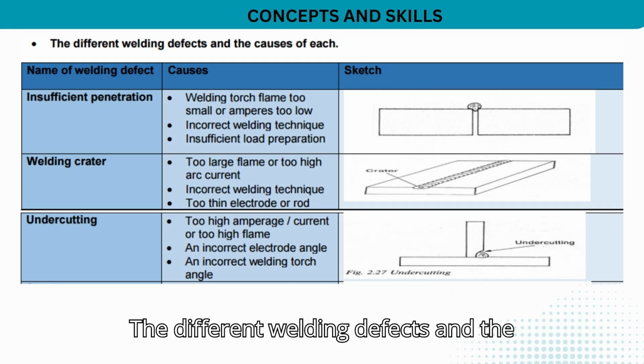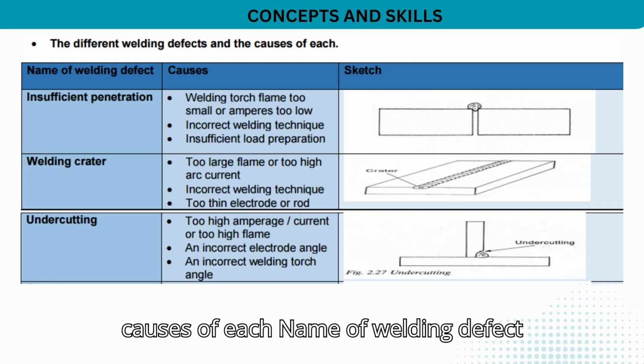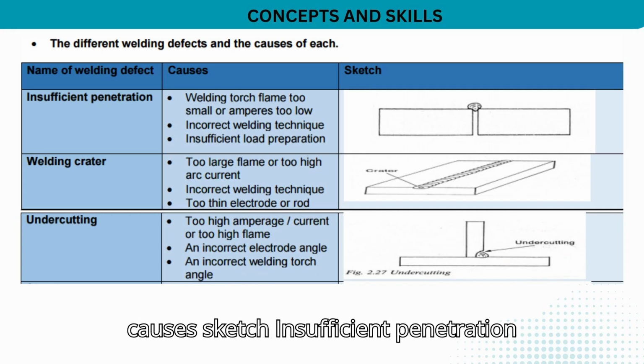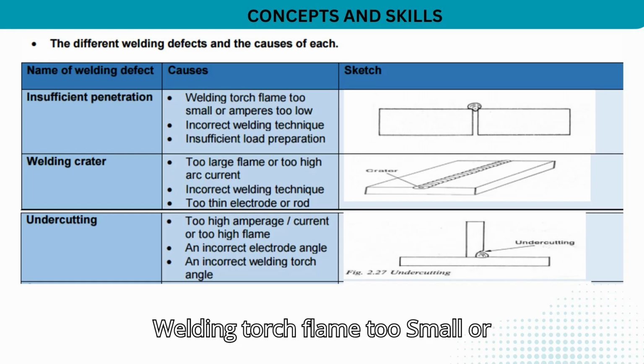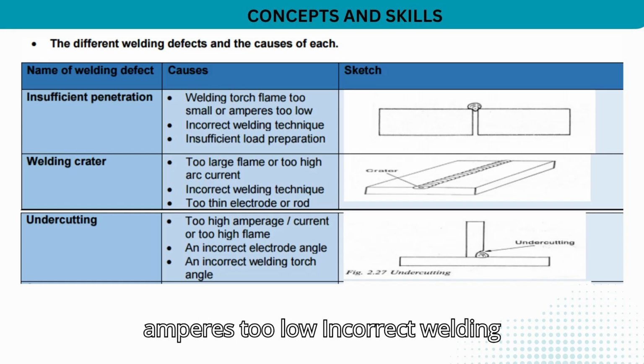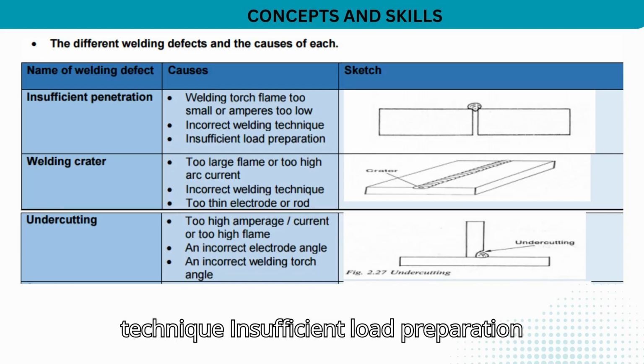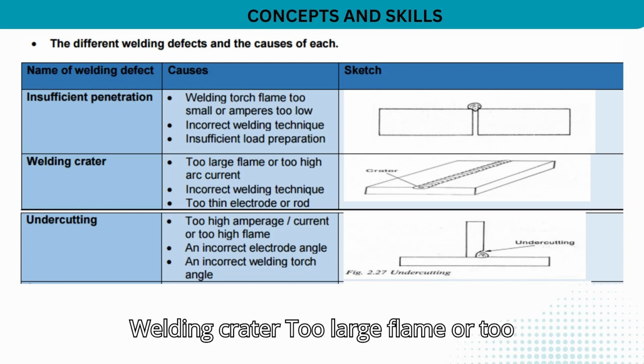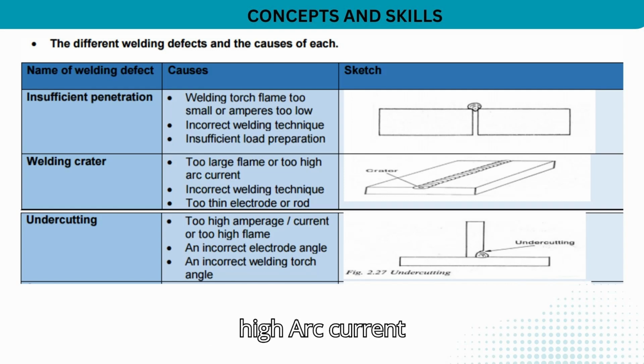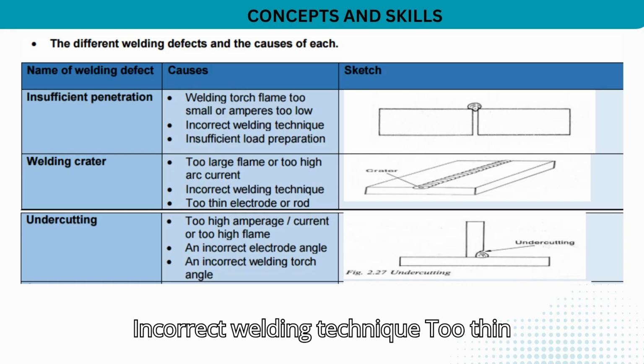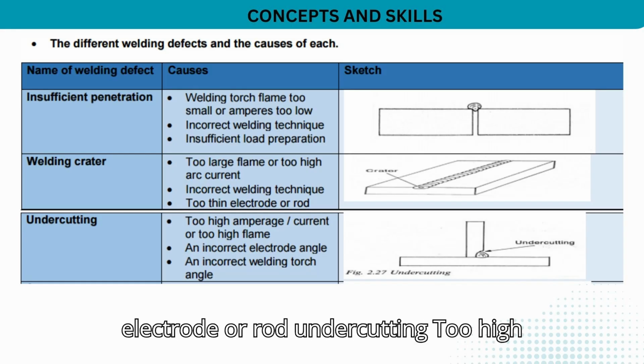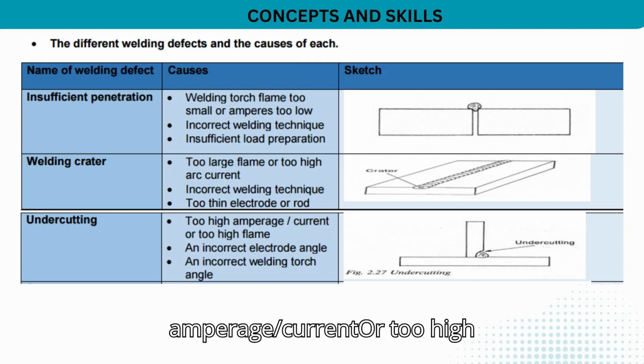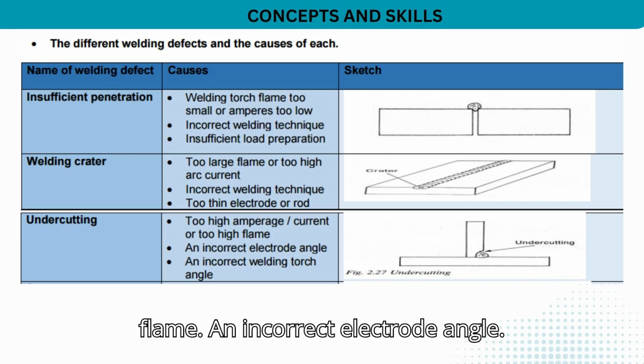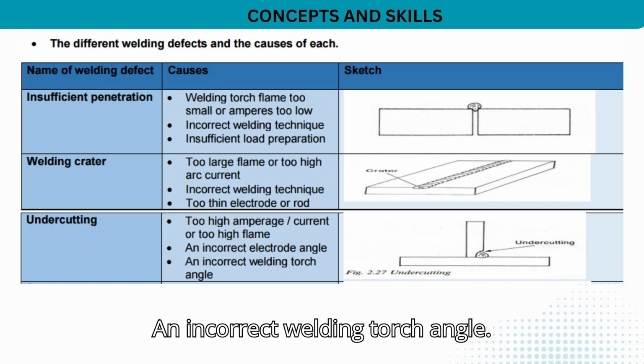The different welding defects and the causes of each. Name of welding defect, causes, sketch. Insufficient penetration: welding torch flame too small or amperes too low. Incorrect welding technique. Insufficient preparation. Welding crater: too large flame or too high arc current. Incorrect welding technique. Too thin electrode or rod. Undercutting: too high amperage or current, or too high flame. An incorrect electrode angle. An incorrect welding torch angle.